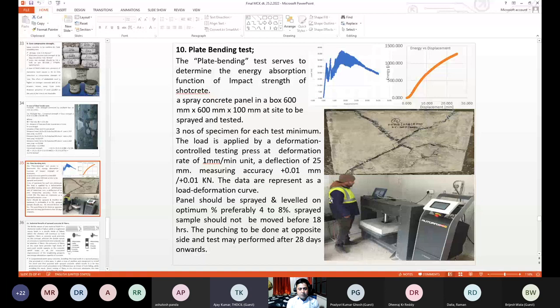not earlier than that. You are visualizing the load upon displacement. It directly comes on the screen of the machine, and you can calculate the energy, or the machine shows the energy directly, because well distributed fibers give you better energy. In case your accelerator dosage is perfectly okay, your fiber is well distributed, and your finishing is good, you can achieve good energy. The results can be calculated, or the energy is basically the load area under the curve is the energy.